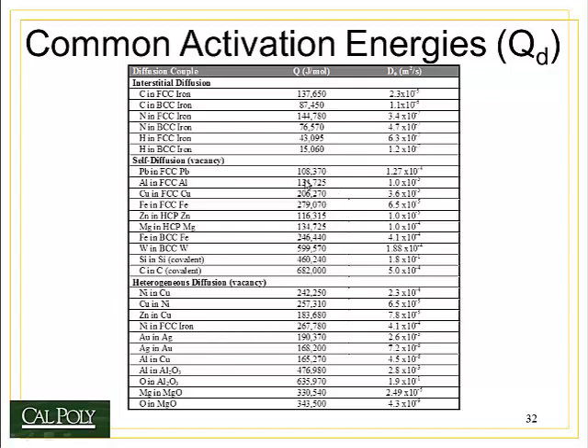Lead has the lowest activation energy of all the metals listed here, at 108,370 joules per mole. Going to aluminum, the activation energy goes up, and copper is even higher, and iron even higher than that. If we were to plot this data as a function of melting temperature, we'd see an almost linear relationship between activation energy and melting point. Higher melting point metals have stronger bonds, and therefore lattice distortion increases the system energy even higher, making diffusion more difficult.